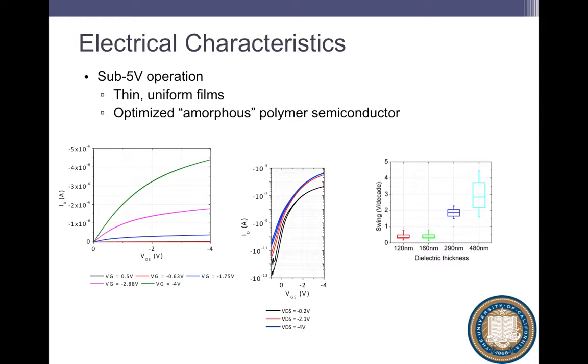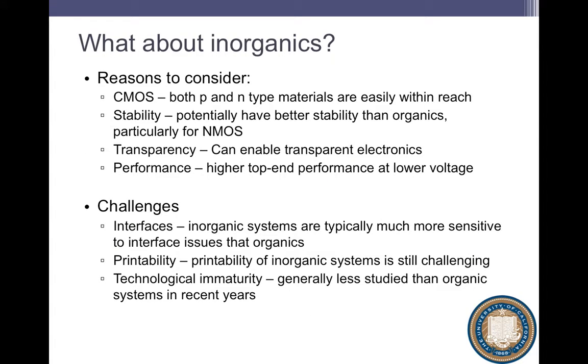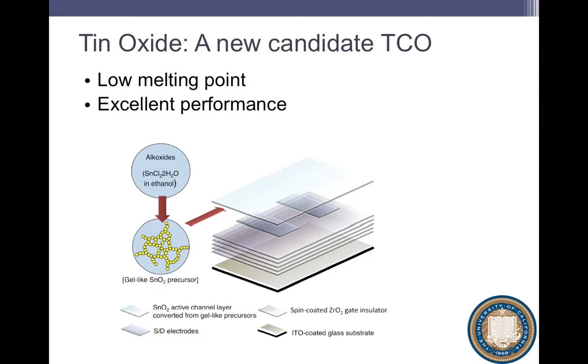Now, these are organic transistors, so they're printed using polymer materials for the dielectrics and semiconductors and nanoparticles for the electrodes. But it turns out we've moved far beyond that. In particular, in my group, we focused a lot on printable inorganics. And the main reason is really performance. It turns out organics hit an upper limit at a mobility of about 1 to 5 centimeters squared per volt second. With inorganics, we're running at several tens of centimeters squared per volt second. So the particular inorganic that my group has had a lot of success with is tin oxide.